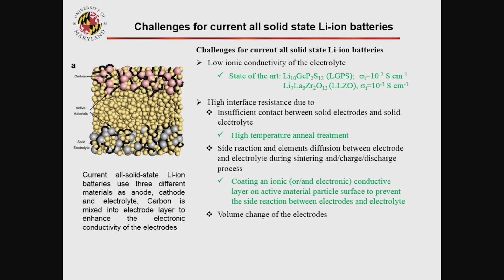But they have limited success. And another challenge is the volume change. The electrolyte's volume does not change, but the electrode's volume changes. So the active material changes volume, but the solid electrolyte volume does not change. If one side changes and the other does not, the interface resistance gradually increases. Right now the technology forms a porous structure. But with porous structure, it is still the same. Even though it allows volume change and reduces the stress, the interface between them still gradually increases.